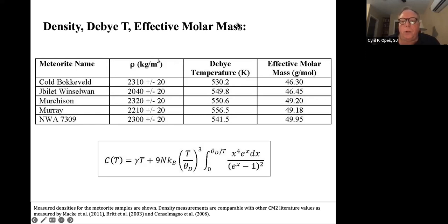And the fact that these are not very high means that there's a certain level of stiffness, but as the Debye temperature rises, that usually says that the material is very stiff. For quartz, which is a very stiff material, the Debye temperature is a lot higher.